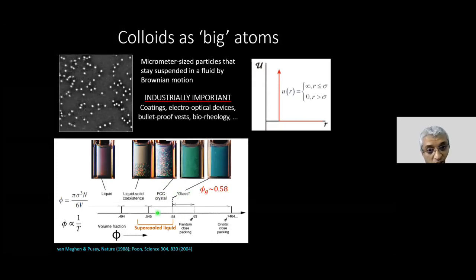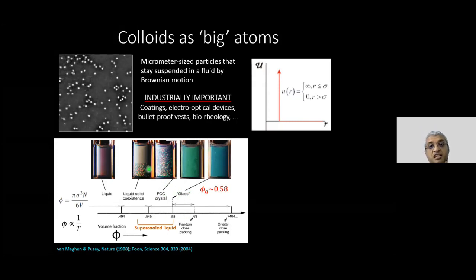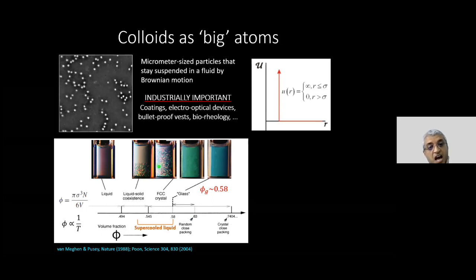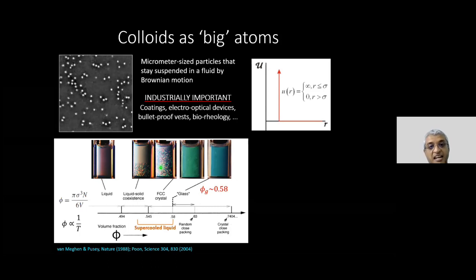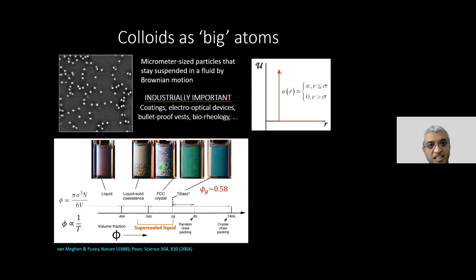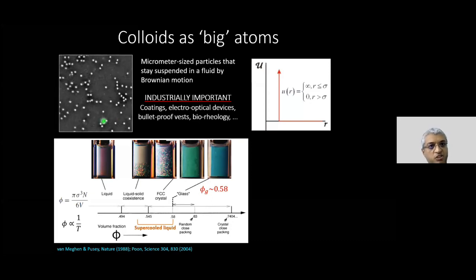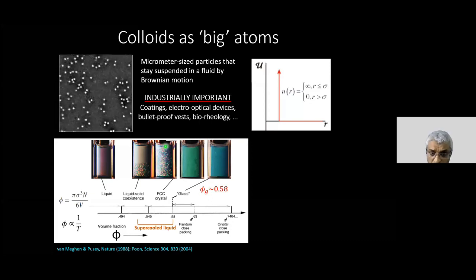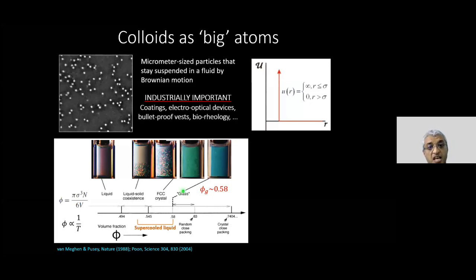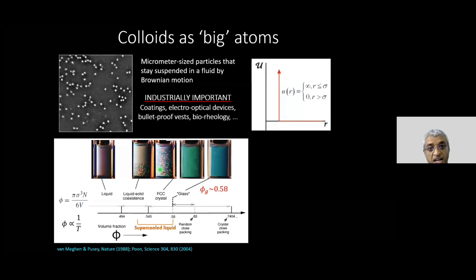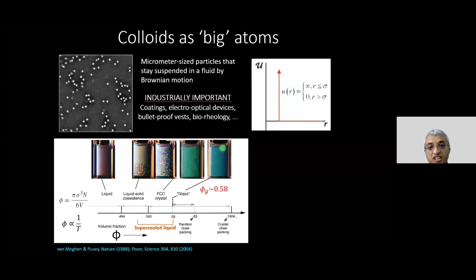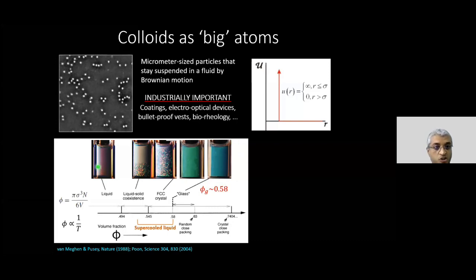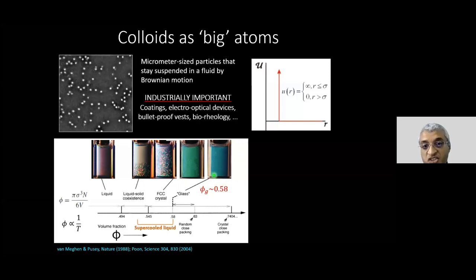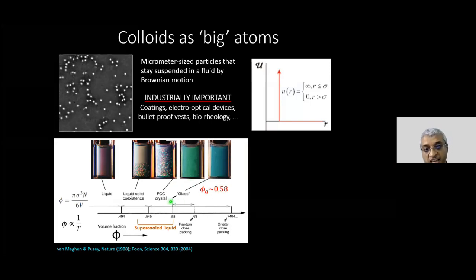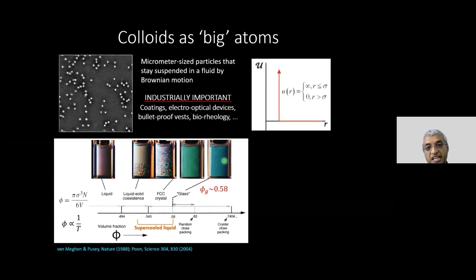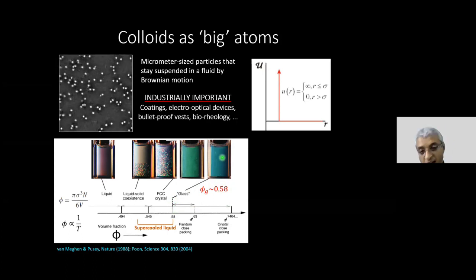But experimentally, what they found is that when I get into this regime, you see these colors that you see here, which are basically colloidal crystals scattering visible light. You see, the colloids are about a micron in size, so the relevant X-ray wavelength would be visible light for these particles. So they're just scattering visible light, just the Bragg diffraction coming out of colloidal crystals. But then you will see that as I increase the volume fraction, I don't see crystalline, but I once again become this homogeneous looking suspension, which is just looking like the fluid. And this is essentially the glassy state. So if I take hard-spheres and keep packing more and more of them, at about 58% I start ending up with a glass transition.